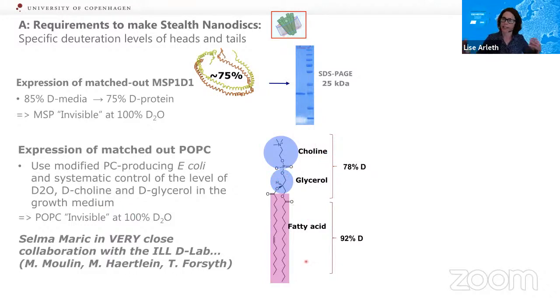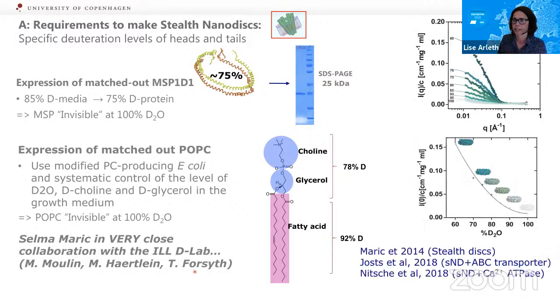And this implied that it becomes overall invisible on all the length scales. So both the head groups and the tails then match out separately. And of course, the whole thing also matches out separately in 100% D2O. All this work was carried out via tour de force by Selma Maric, and it was carried out in very close collaboration with the ILL D-Lab with Martin Moulin and Michael Haertlein and Trevor Forsyth.